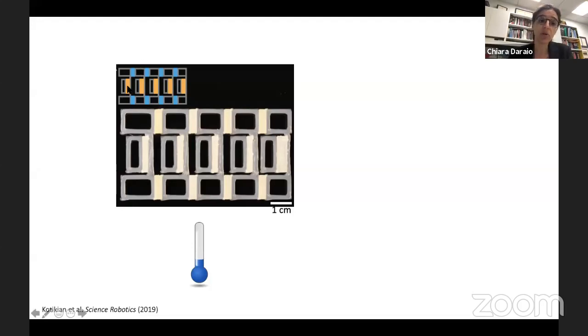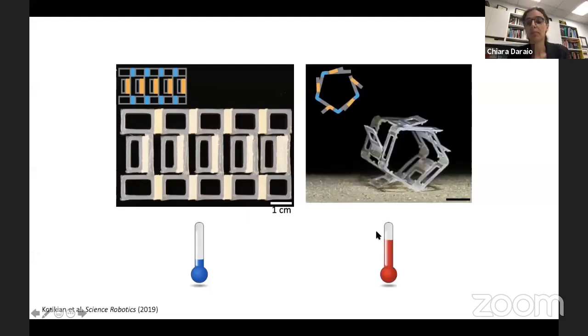Then you see these blue and orange areas that you see here and here, which are liquid crystal elastomer hinges that respond to different temperatures. And you can see that we use one for the side branch and for the side lobes, and the other for the middle part. So when this sheet is cold at room temperature on a table, it remains flat. But when the temperature is increased, it rolls up a bit like a roly-poly and morphs into a different shape.